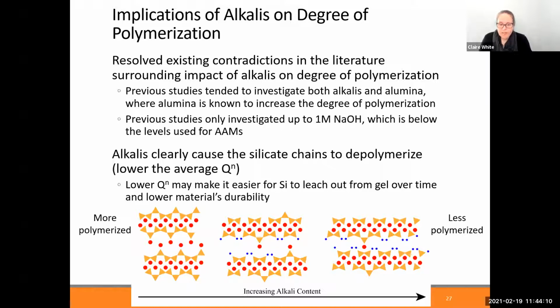And so this is what we've found: the more polymerized, the less sodium; the more sodium, the less polymerized. So we have resolved existing contradictions in the literature surrounding the alkalis and the degree of polymerization. Mostly in the past, people have studied both sodium and aluminium at the same time, where aluminium is known to increase the degree of polymerization.